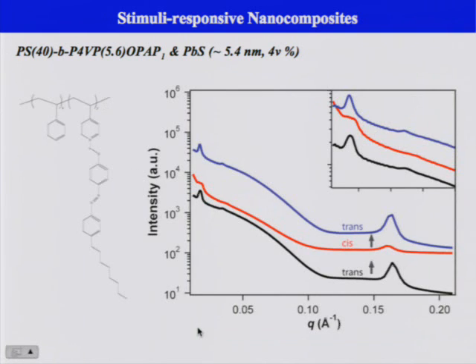That's what you see here - looking at the small angle X-ray scattering, which essentially tells you the particle spatial distribution. You go from trans to cis, and then you can actually go back to trans again - the process is reversible. Overall, this shows that you can indeed use light to control particle assembly within the nanocomposite.